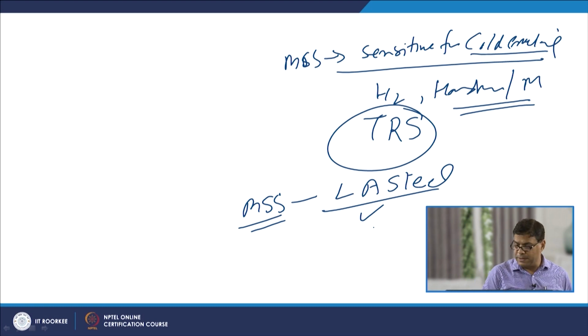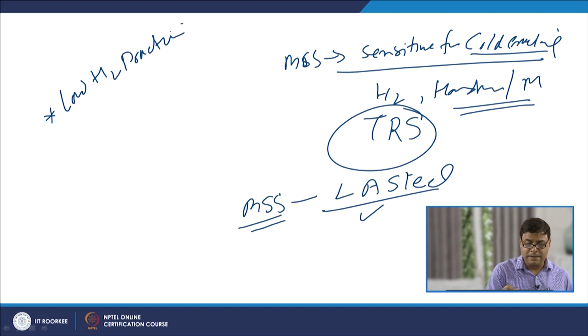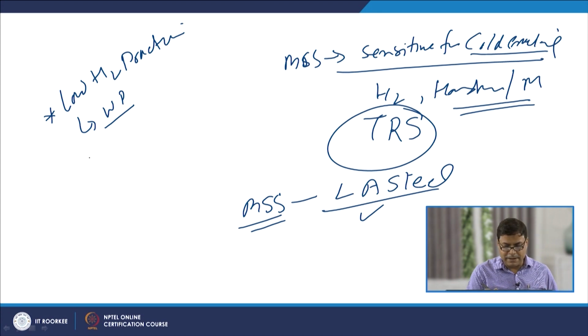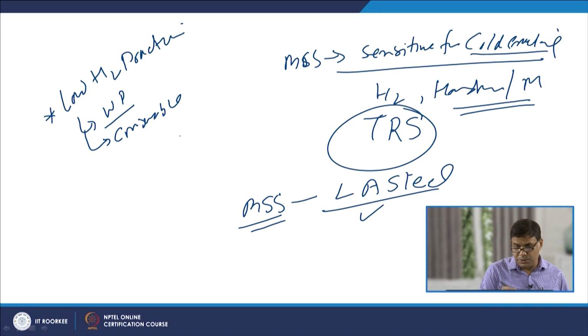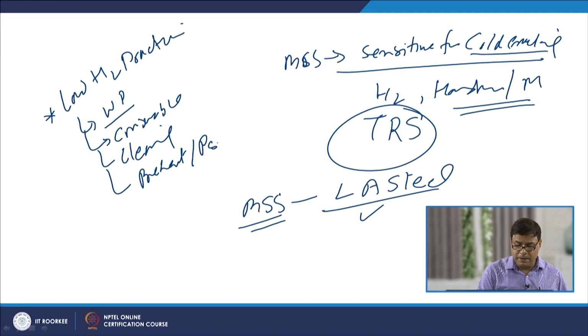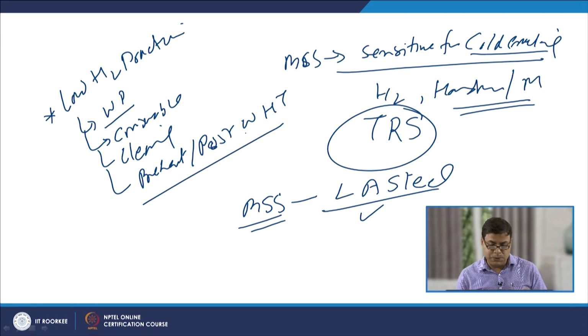And what we have in our procedural aspects is that we have to use low hydrogen practices, which include the use of suitable welding processes that generate less hydrogen in the weld zone, leading to a lesser content of hydrogen there; the use of suitable consumables in the form of shielding gases or electrodes so that hydrogen does not get in; proper cleaning methods; proper preheating and post weld heat treatments, so that whatever hydrogen is there gets enough opportunity and scope to escape from the weld metal as well as the heat affected zone, so that the cracking tendency can be reduced.